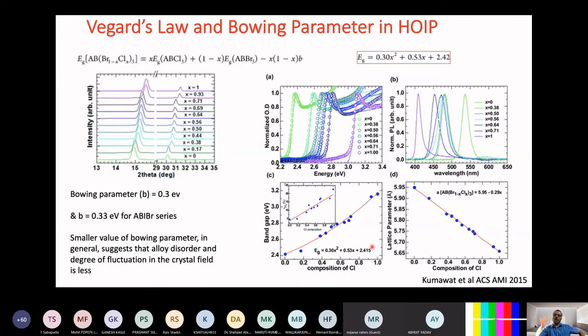So these two data sets are plotted here, and we could show that the alloy disorder is very low in these semiconductors. You are alloying, mixing MAPbCl3 with MAPbBr3. You have ABX3, where AB is MAPb, and X is chlorine and then bromine. And you are tuning this to see how the band gap changes, and you are looking for this bowing parameter. The bowing parameter, just 0.3, is even lower than the MAPb I-Br series, and much lower than the gallium indium nitride series. That suggests that these materials are mixing well. They are not introducing any kind of alloy disorder, and the degree of fluctuation in the crystal field is very small.